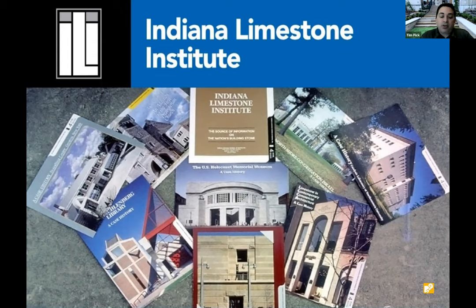With the Royal Alberta Museum, we showed that picture early on, and that was a gray stone. And gray is difficult when you're doing panels, as there's a higher moisture content in the stone because it's usually saturated with water when we quarry it. So as that organic matter comes out of the stone, that color can change. So gray can change quicker than other stones, especially on that project.